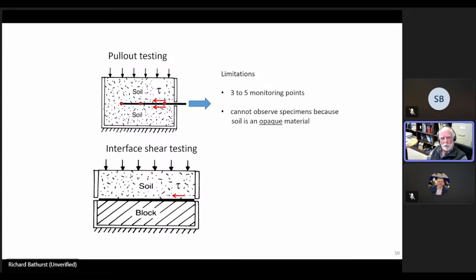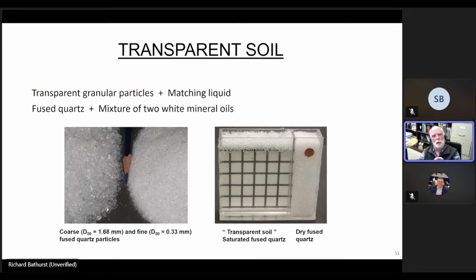So one of the things that we did, which is sort of fun, is we developed a transparent soil methodology. And what we did is we took a dry fused silica quartz material and we mixed it with a fluid which has the same refractive index. And the outcome is that when the soil is dry, it looks a little bit like granulated sugar, but when you inundate it with this matching liquid, it becomes transparent and you can see through it to a certain distance. So for example, you could observe the presence and the behavior of a geogrid which is embedded in this material.